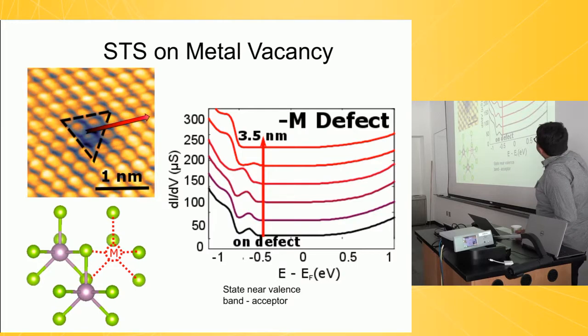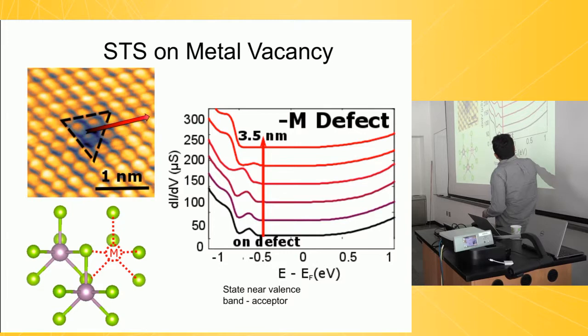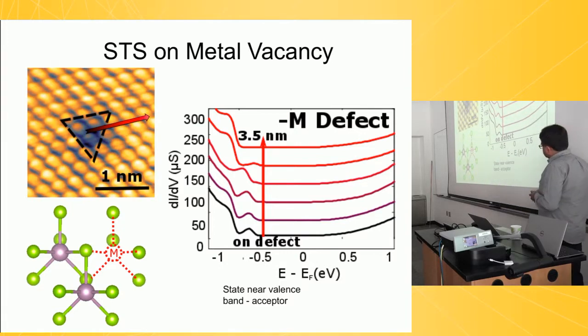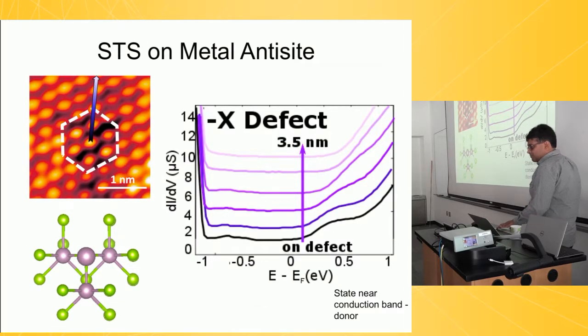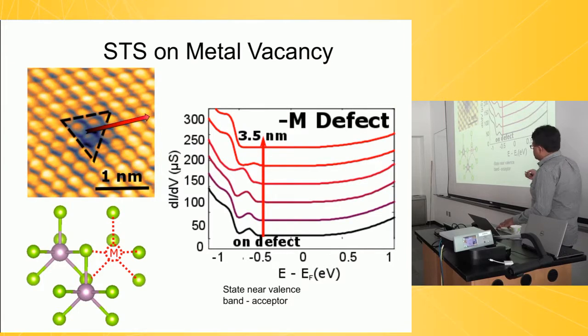We can do the same thing on the metal vacancy. So here is the metal vacancy, and in this case, you see a nice state. This state is close to the edge of the valence band. Once again, about 3.5 nanometers away, the impact of this state is gone. So the metal vacancy acts as an acceptor, and the chalcogen anti-site acts as a donor. If you think about what these things are chemically, for five minutes, you'll realize that this assignment makes sense.